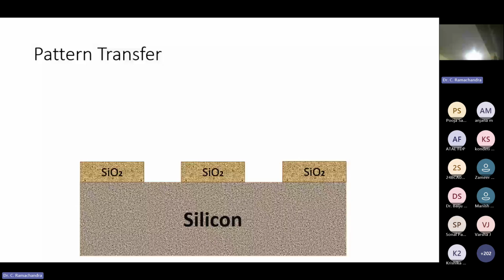So now I have silicon with patterned silicon dioxide over it. That means I transferred the pattern from mask to the photoresist, now photoresist to the silicon dioxide. Now I am etching the silicon. Wherever silicon dioxide is there, it will block. I am using certain plasma ions. So wherever silicon dioxide is not there, it will etch. So when I etch the silicon in this condition, only silicon which is present where oxide is not there is going to etch. So that is the pattern I'm going to see. Now silicon is etched only in certain locations. So now the job of silicon dioxide is done. So I'm going to remove the silicon dioxide again by chemical etching. So this is the pattern.